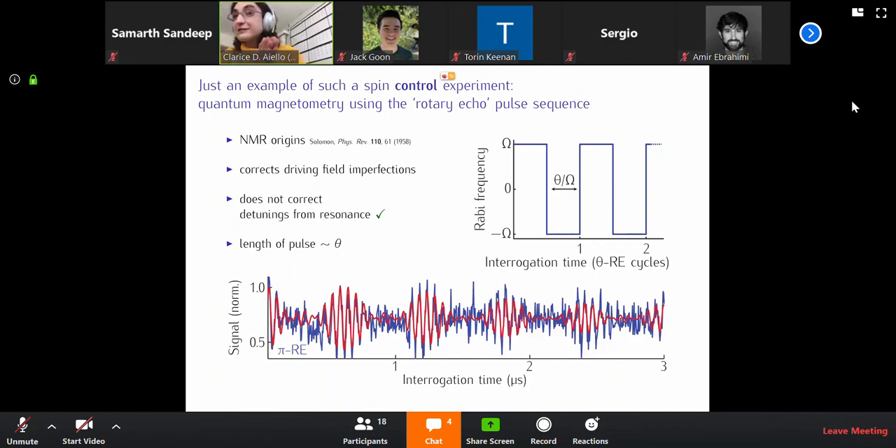One very common source of noise is spin noise — the noise that comes from interactions with other spins in the carbon lattice. There are substitutional phosphorous spins, carbon-13 spins, and all those interactions are going to make your sensor work not as well. That's a reason that really good diamond sensors are made in isotopically pure diamond, where carbon-12 doesn't have a spin. So if you only have carbon-12 atoms, your sensing electronic spin will not suffer the effect of what's called the spin bath.